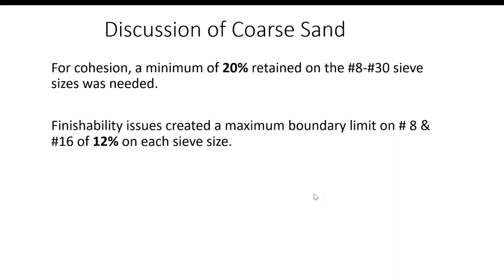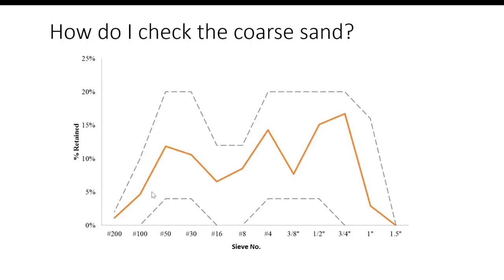So this coarse sand, you need a minimum 20% retained on this 8 to 30. And for finishability issues, if I get above 12% on this 8 and 16 sieve, you get finishing issues.